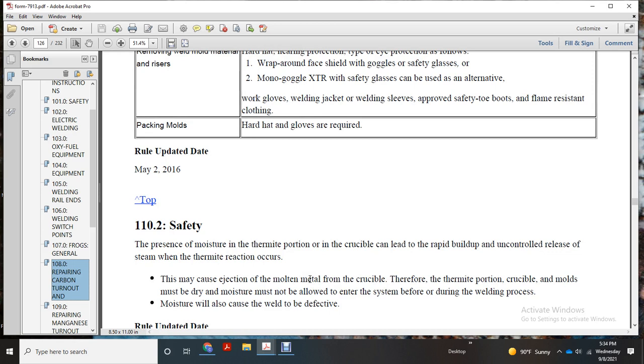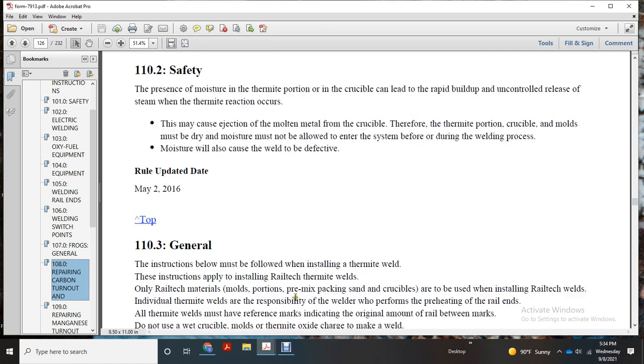Safety. The presence of moisture in the thermite portion of the crucible can lead to a rapid buildup and the uncontrolled release of the steam of the thermite reaction, and may further cause the ejection of molten metal from the crucible. Therefore, the thermite portion, crucible, and mold must be dry, with moisture not allowed to enter the system before or during the welding process. Moisture will also cause the weld to be defective.